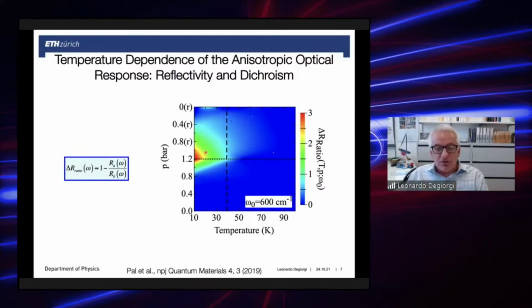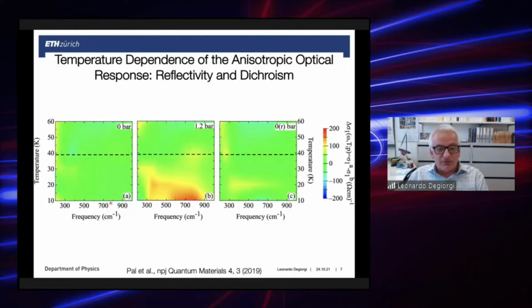You can also now look at the dichroism here as a function of temperature for three selected applied stresses: the initial zero stress, the maximum applied stress, and then the stress released back to zero. And you see that, in fact, you have to go into the superconducting state to see a stress-induced anisotropy in the optical spectra, which, however, is reversible, as I said many times, when you release stress back to zero. The important thing to observe here is that the energy scales affected by the external symmetry breaking field are rather close to the Fermi level. So this means that the uniaxial stress is affecting the conduction bands crossing the Fermi level, and therefore of relevance for the transport properties, determining also the superconducting property.